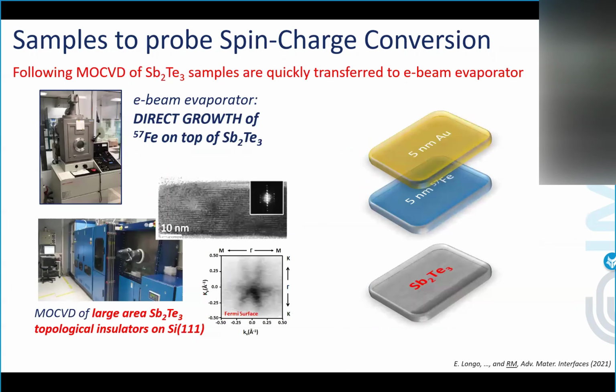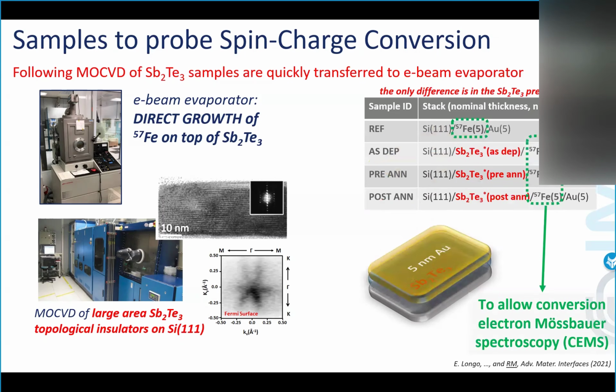Now, what we have done with Mössbauer, of course, you have to interface the ferromagnet with the topological insulator. Being myself a Mössbauer guy, the first thing that I did was to put iron 57 in contact with it. In our laboratory, following the production of topological insulator over quite large areas by metal organic CVD, we moved the samples, and that is one of the issues, to an E-beam evaporator, where we put a very expensive iron 57 target, and we deposit 5 nanometers of this iron 57 on top of our topological insulator, which is antimony telluride, and finally capping with a protecting gold layer.